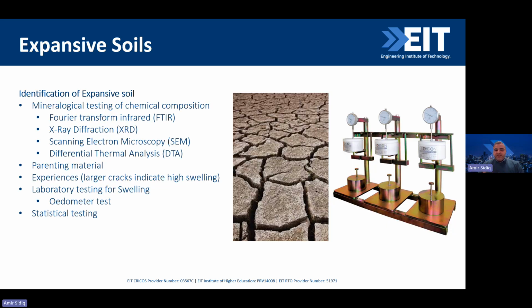So the first thing we need to know is the identification of these particular expansive clays. We have different types of testing to understand the parent material or the actual mineralogy of the clay. So we use FTIR, XRD, SEM, or TGA, DTA. That determines the type of the clay, the mineralogy of the clay. Some other ones we can do by looking at it. For example, from experience, when we see pretty deep and wide cracks in the clay, we know it's shrinkage. So this soil is an expansive clay.